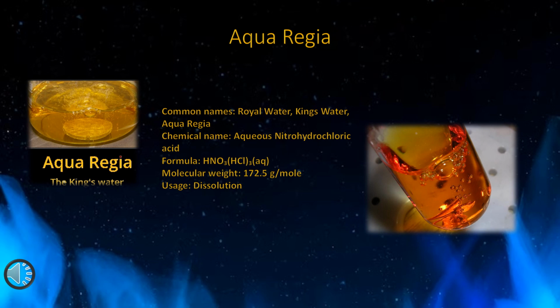A minute amount of silver will start to dissolve. However, a chloride coating will start to form, which inhibits further reaction with the silver. It is this insoluble chloride coating which inhibits further dissolution of the silver.